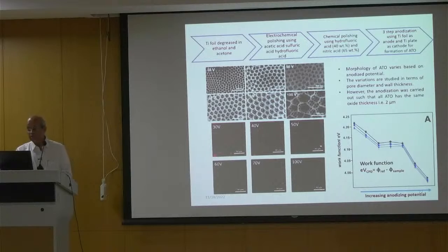This graph at the bottom is going to show you, on the y-axis, the work function of titanium, and on the x-axis, increasing anodizing potential. For example, at 30 volts you get this type of honeycomb structure, then 40, 50, 60 volts. This is the anodizing voltage, and at about 100 volts you get big honeycomb structures.